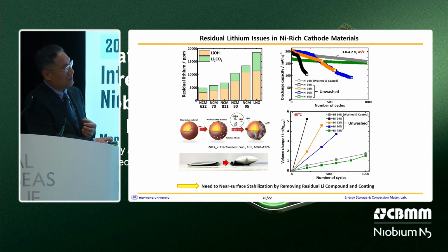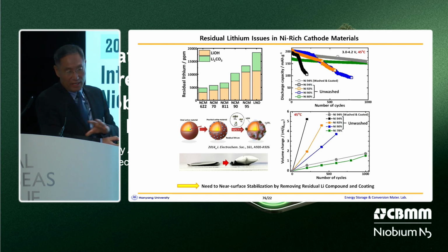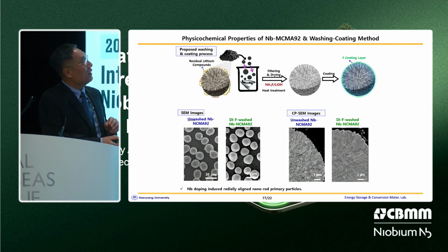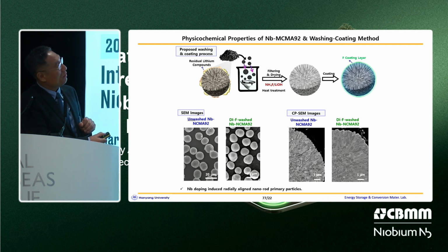Therefore, we need tools for near-surface stabilization by removing residual lithium compounds and coatings. And we wash the cathode material using deionized water, and also we provide a LiF coating layer by reacting ammonium fluoride with the remaining residual lithium on the cathode surface. And as you can see in the cross-sectional SEM image, again, niobium doping induces radially aligned nanorod primary particles.